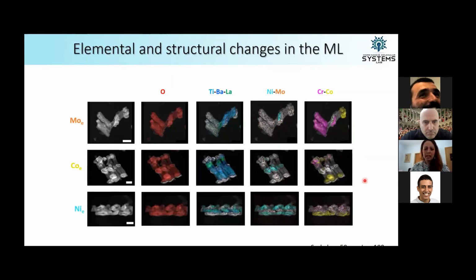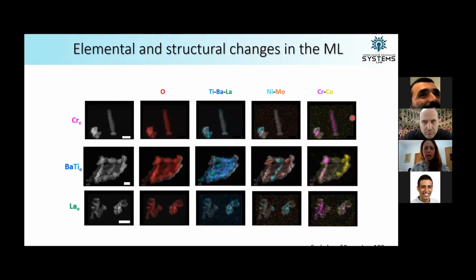From just some EDX analysis on the different structures from the different edges, you can see that some of the elements really interdiffuse. They're completely oxidized, first of all, but some of them interdiffuse. So for example, barium, lanthanum, and titanium interdiffuse throughout the whole area of the nanostructure in all the shapes. But if you look at nickel, for example, or cobalt, they're very localized into small cluster areas. And this really happens for all the different types of shapes.